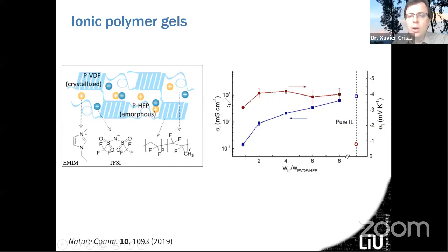Now we can look at the Seebeck coefficient of the ions, and we see a parameter close to -4 millivolts per Kelvin. It is a very high value. If you just take the pure ionic liquid, you get much lower—less than -1 millivolt per Kelvin. So the fact that this ionic liquid is in the polymer matrix boosts this ionic Seebeck effect.